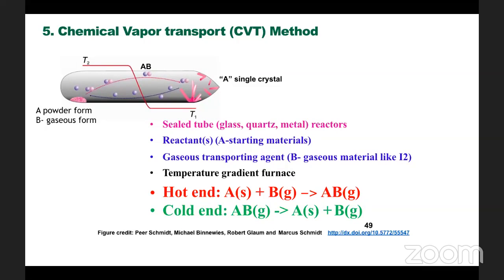In the hot zone, we have to take our powder, the material which we already prepared, a pure-phase material. You keep this end at the higher temperature, and the other end at a cold temperature. Along with your material, you have to choose a transport agent like iodine or barium chloride. Based on your material, you have to choose the transport agent. The reactant plus your gaseous transport agent combine together and form a gaseous state. In the cold end, you will get very nice crystals plus gases. When you cool down, it all condenses.